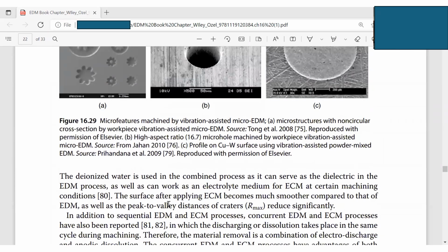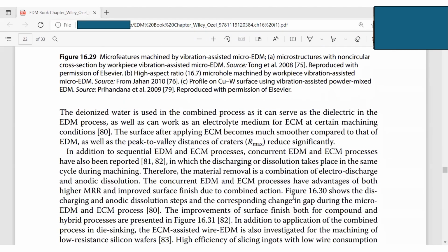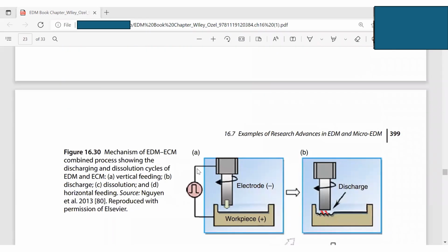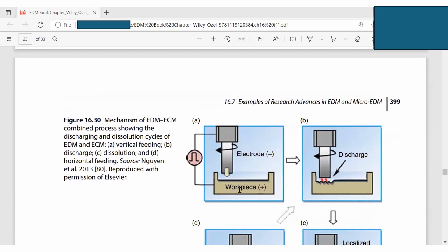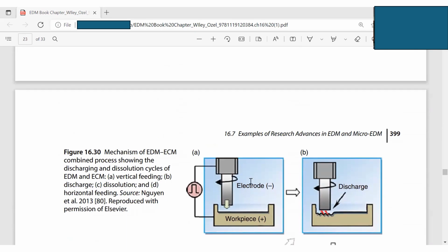So the surface after applying ECM becomes much smoother compared to that of EDM, and the peak-to-valley difference of craters is reduced significantly. So this is ECM. This shows the workpiece, this electrode, and also this is the electrode within here, and we have some deionized